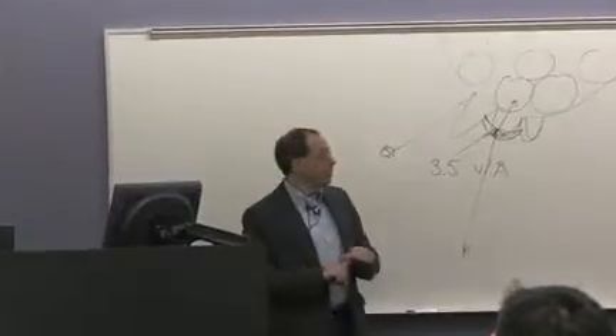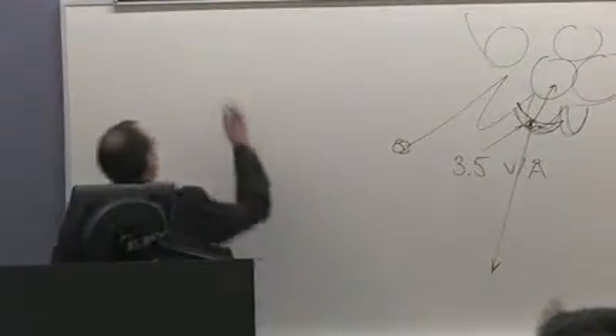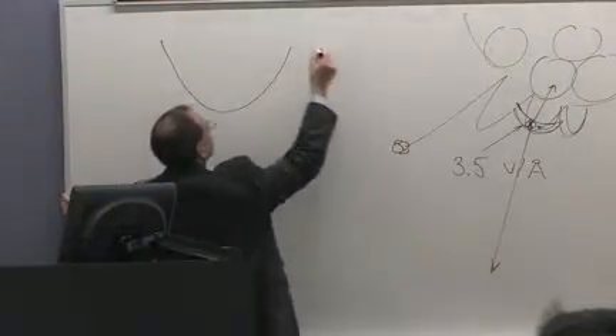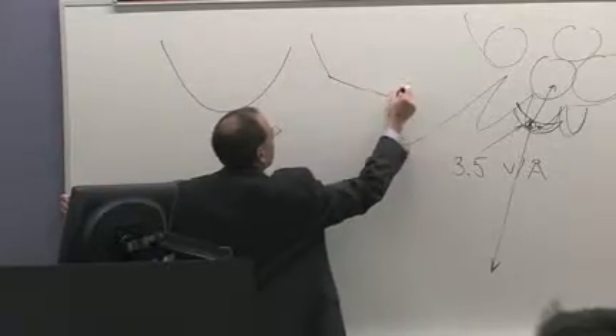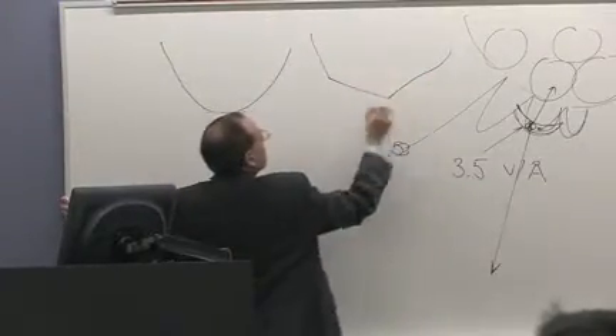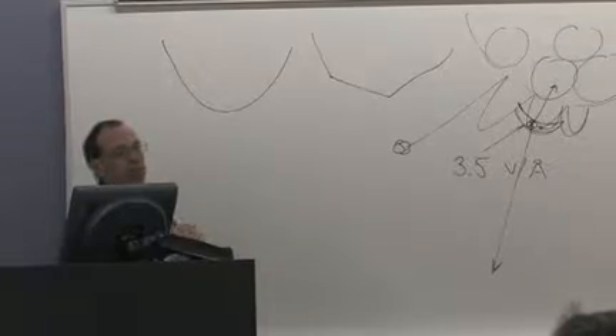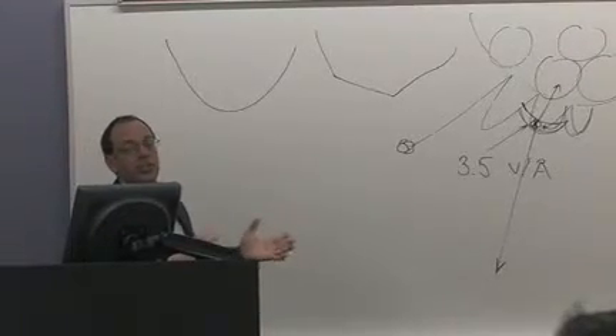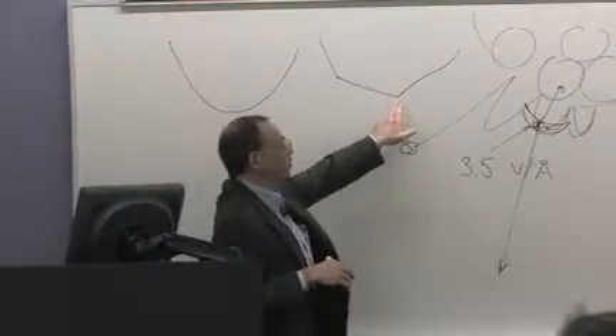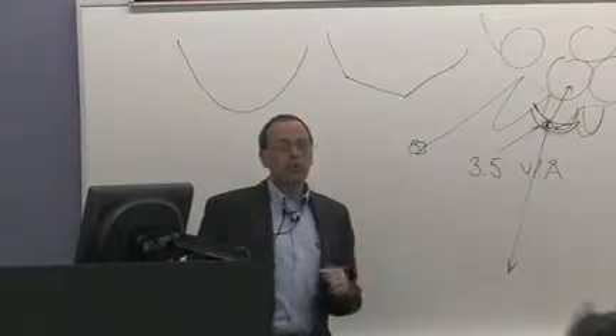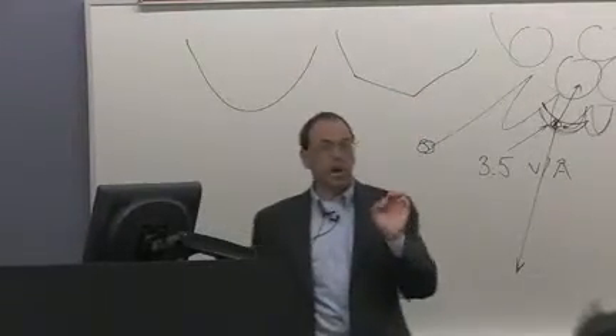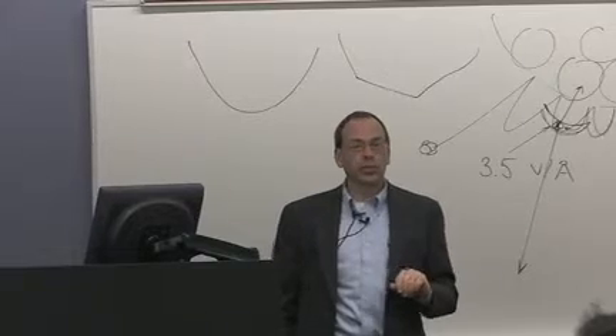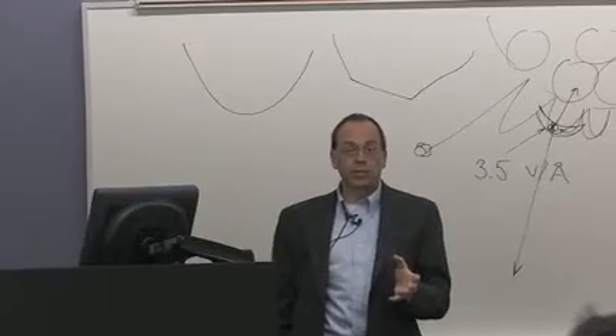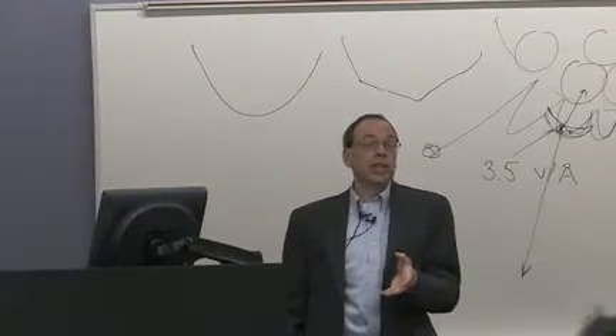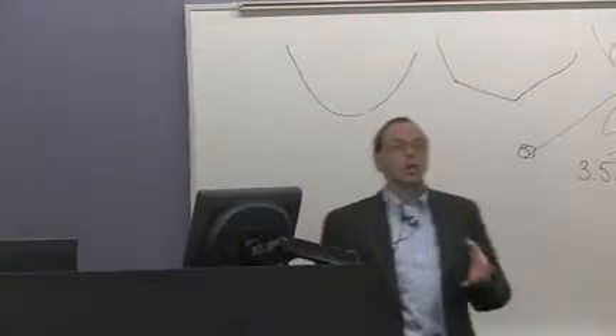We had to be able to get that tip from a rounded shape like this to this faceted shape like this, where we have a single apex at the end, and be able to go back and forth. So we had to develop that in situ. Those atoms that are very much at the apex may last only for a week. That atom will actually pop off in time. It's almost unavoidable. The lifetime is typically from 3 days to sometimes 3 weeks. A single atom will stay there. Once it pops off, we have to do a reforming.